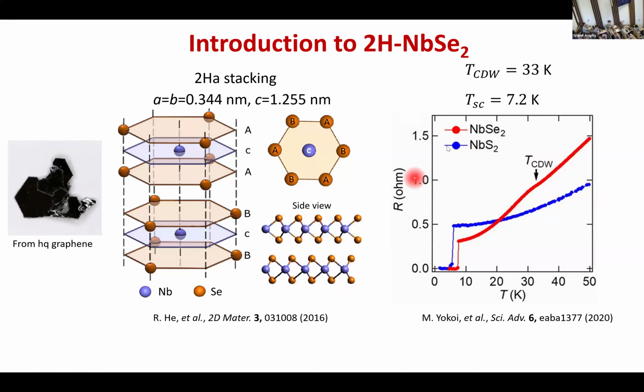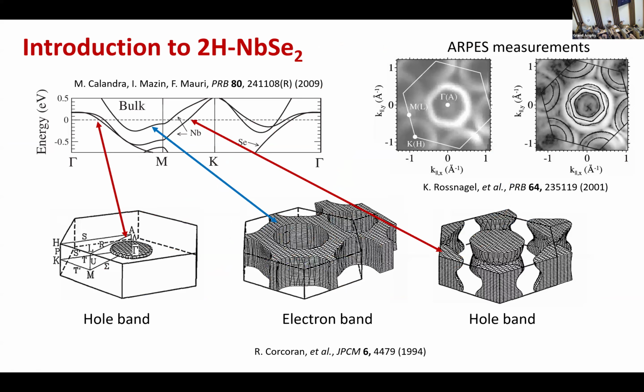And this system has a TC of 7.2K. And also it has a charge density wave around 33 Kelvin. This is pretty established. So for this particular system, the idea is that this is a layered system, so one could really exfoliate and go to the monolayer. The band structure looks like this. It's a kind of complicated band structure with essentially a hole band around the gamma point, another bigger hole band also around the gamma point, an electron band, and also another hole band around the K point.